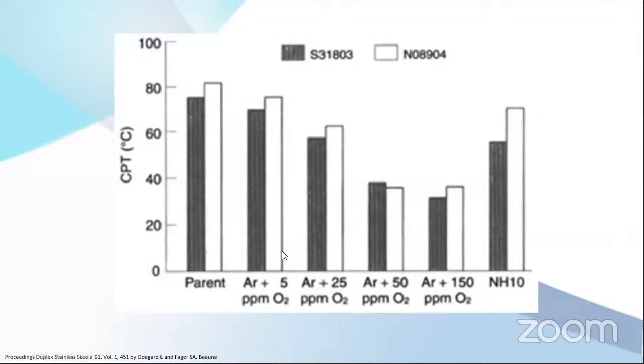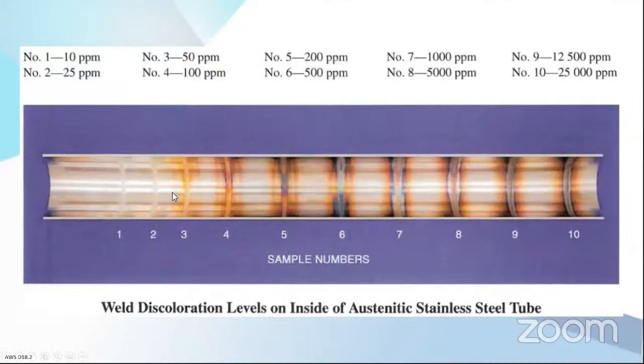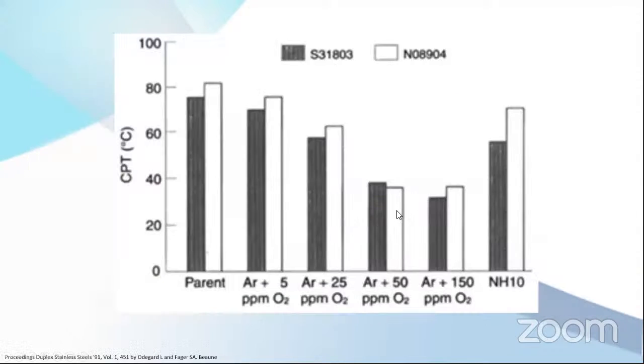They have a very high temperature before the metals experience pitting. And this is the welding gas argon with 5 ppm oxygen. So there is a reduction, but not a lot. But if you see here, if it reaches 50 ppm oxygen, it's almost half of the original corrosion resistance. So in the application during service, it can get corroded very easily, very fast. This is the 50 ppm O2, and 50 ppm is number 3. Even this is not accepted. It can cause a significant corrosion problem in the weldment area.